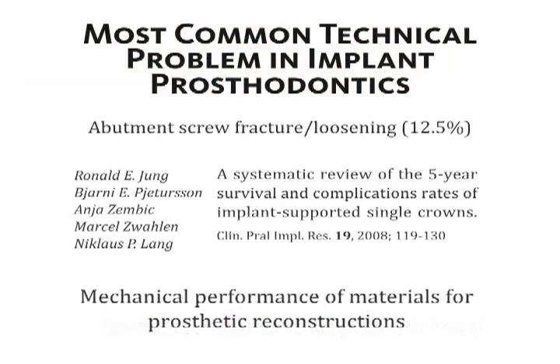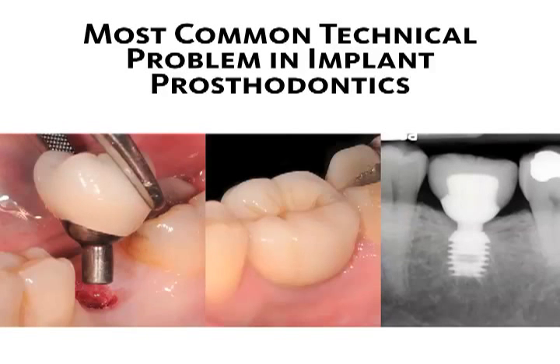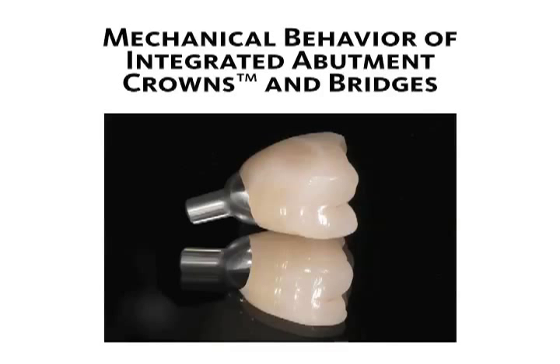So the literature shows that the most common technical complication in implant prosthodontics is abutment screw fracture and/or loosening, which happens in 12.5% of the cases in the 5-year follow-up range. Since the locking taper implant abutment connection does not involve screws, we will focus on the mechanical performance of materials for prosthetic reconstructions and more specifically to the mechanical behavior of the integrated abutment crowns and bridges.